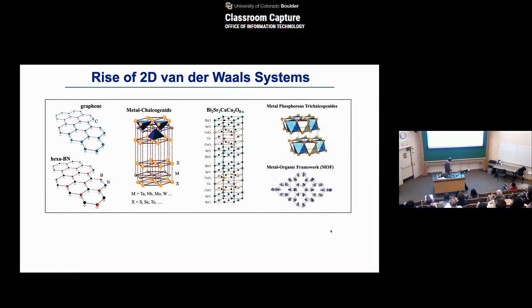Turns out that some of the known materials, including the high temperature superconductor, often consist of layered systems, where all the chemical bonds are within the layer, but between the layers a weak van der Waals force holds them together. So in principle, you can extract this material down to a single atomic layer, or you can grow them in some cases. But the important part is that down to a single atomic unit cell, the material can be stabilized. I think that's a very important part, such that experimentalists can now put their hands on this material